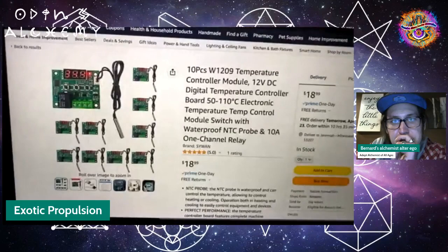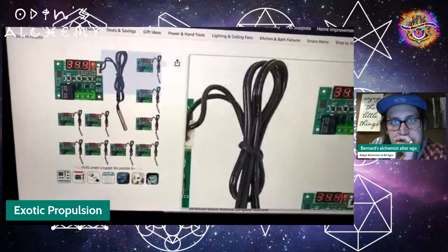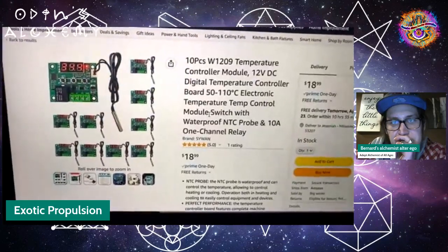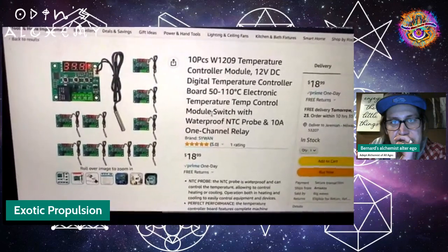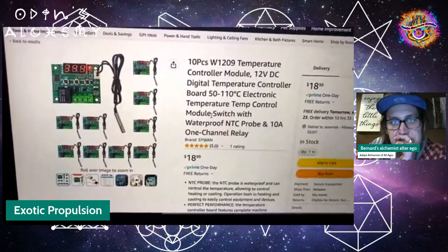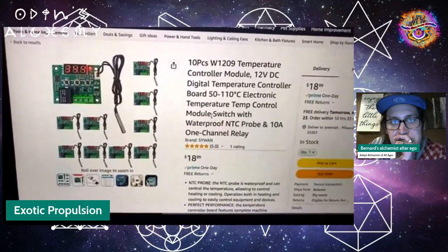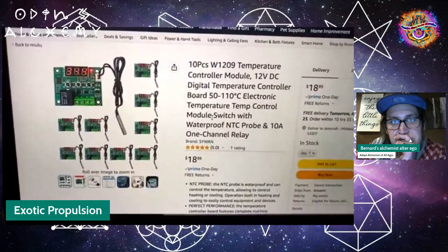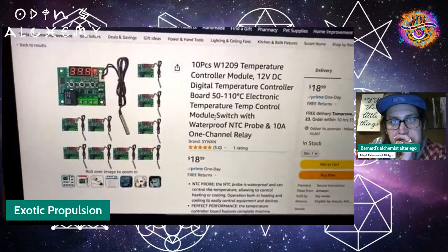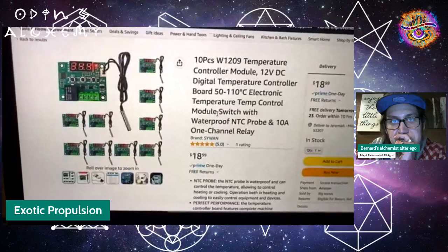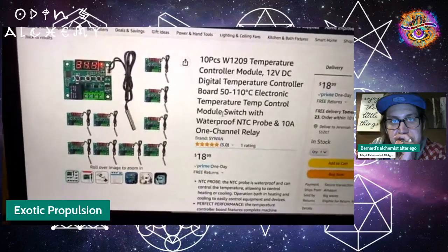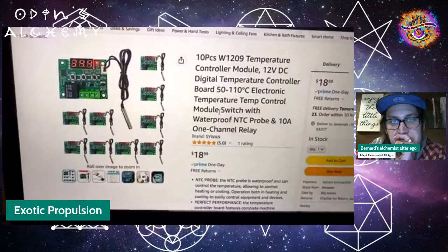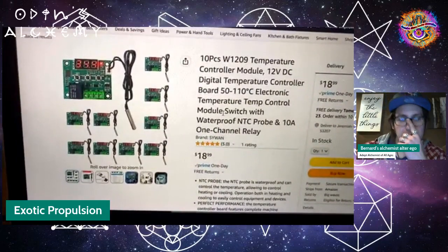So I'm going to get this 10-pack here and arrange it with all these heat pads on each of those grow trays that we just looked at. And this will allow me to keep them very stable above ambient and slowly decrease the temperature as the crystal gets larger, so that we'll finally be able to grow them significantly larger and get a lot more out of the same volume instead of having to grow them at room temperature and letting them naturally generate themselves.